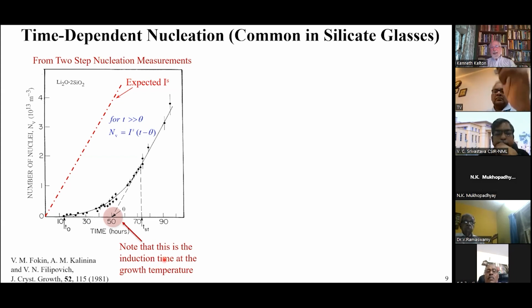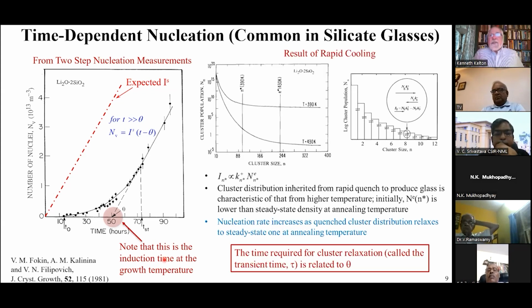Now, why would you expect to have a behavior like this? Well, I can explain it qualitatively in this way. Remember that I said that the nucleation rate is proportional to the forward rate constant times the equilibrium distribution. So if you think about quenching a glass, what you're going to do is take a high temperature distribution, you're going to quickly lower the temperature, and you'll end up getting that distribution at the lower temperature. It will want to change. For example, if I have a distribution at 430 Kelvin from a quench, and I quench it to 390, it will want to have this distribution, not that distribution. The only way that that can change is through the bimolecular rate kinetics.